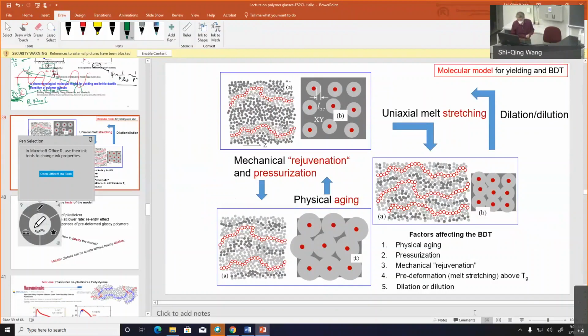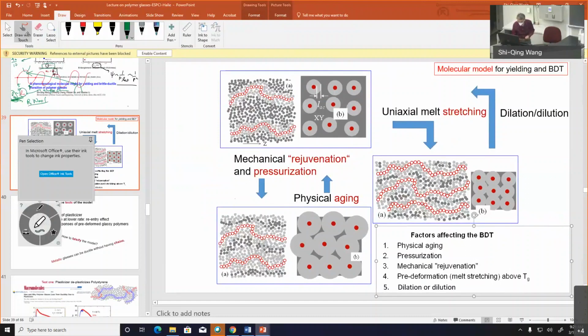By what? By, for example, melt stretching. In other words, if you have a ductile polycarbonate, you age it so that ductile polycarbonate becomes brittle. Well, the only way to overcome that is I take my polycarbonate, I first melt stretch it. Then even when you age your polycarbonate, it will still remain ductile, because I have improved my network. So even though the soldiers are more dormant, you still will be able to wake them up. So this is quite obvious.